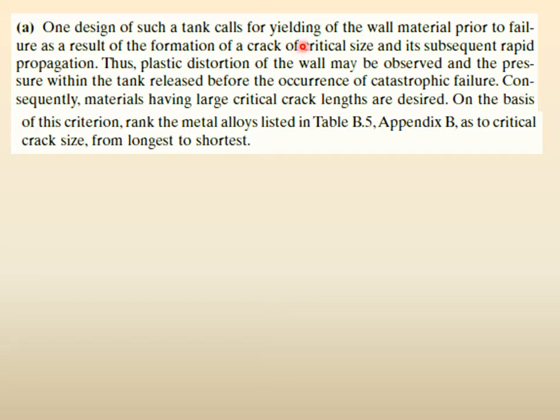So you find out what is the critical crack, then you know that it can keep on deforming. It will not fail until it reaches the critical crack size. The plastic deformation of the wall may be observed, and the pressure within the tank can be released before the occurrence of the catastrophic failure, because now it is yielding, it is changing in shape. So you can close the pressure, you can remove the pressure vessel, whatever.